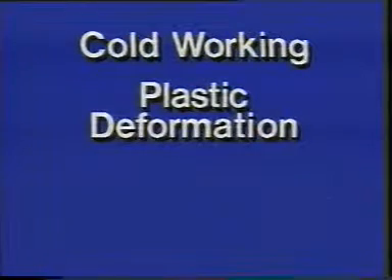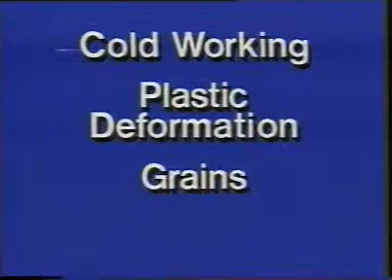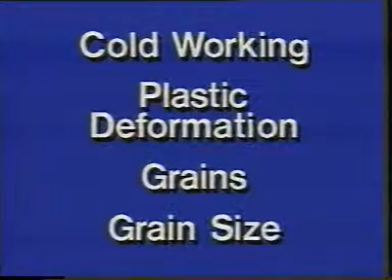Cold working increases a material's ultimate strength and yield strength, though not to as great a degree, and decreases ductility or elongation. Plastic deformation occurs as slip, twinning, or creep. Grains or crystals offer opposition to slip, causing the deformation to increase hardness of the material. The finer the grain size, the more interference to slip, and therefore the higher increase in hardness and strength from deformation.